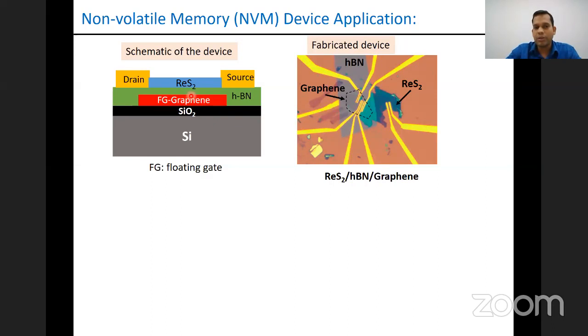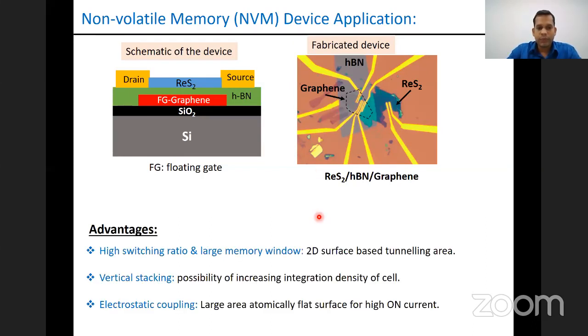So basically now we have this type of device, which is shown in the schematic diagram. And if you see this graphene, it is a floating gate, and there is no electrical contact. Basically, it is isolated from this ReS2 channel with a thin layer of hexagonal boron nitride. And that leads to various advantages, because it is a 2D surface material, and the heterostructure forms a 2D surface.